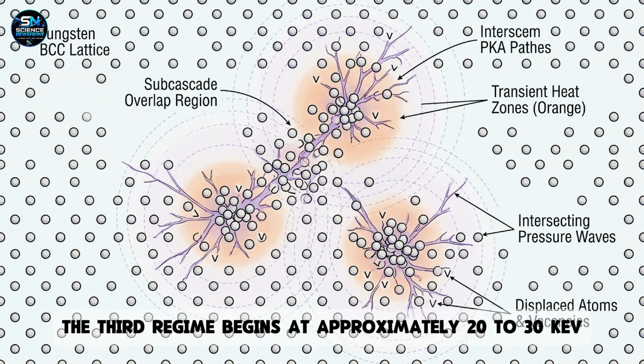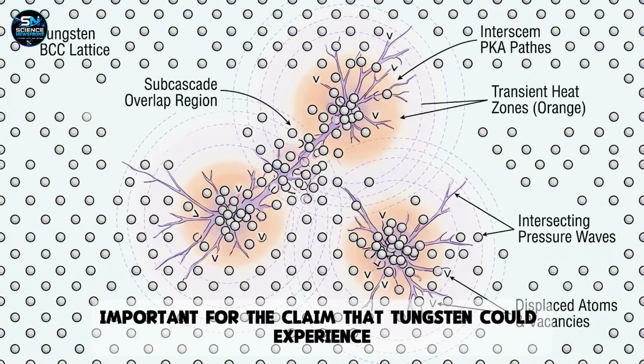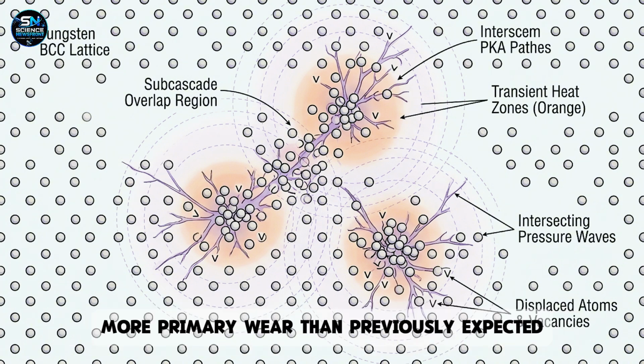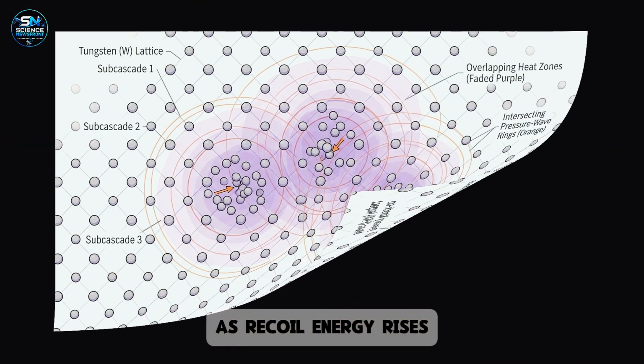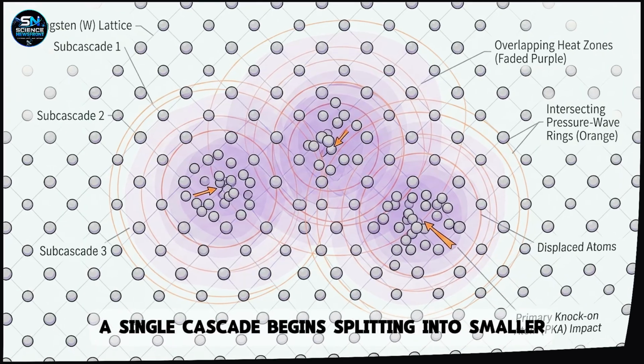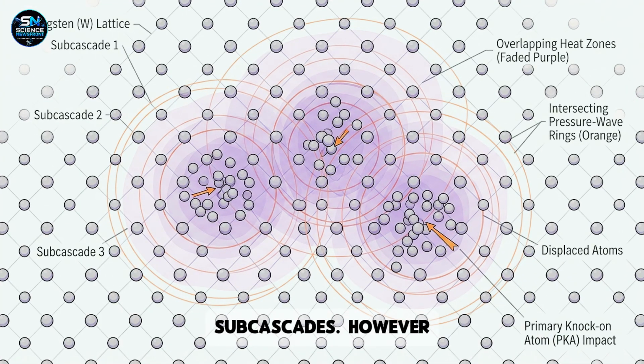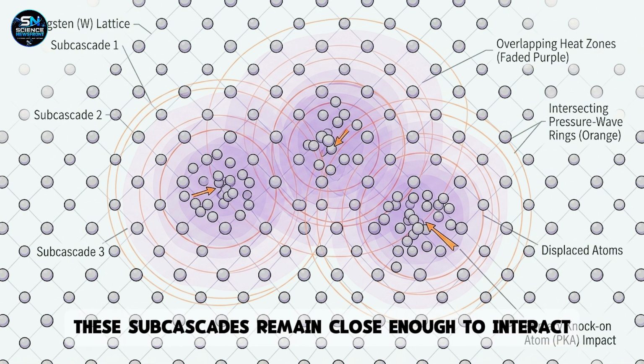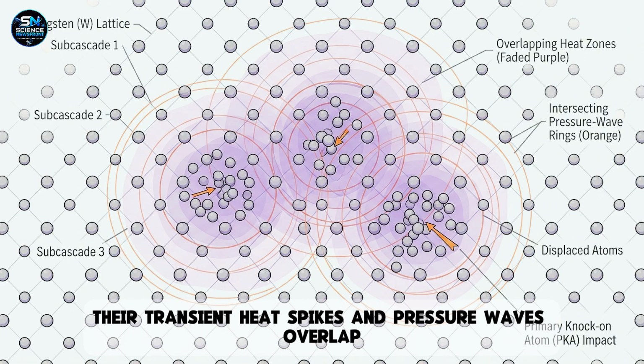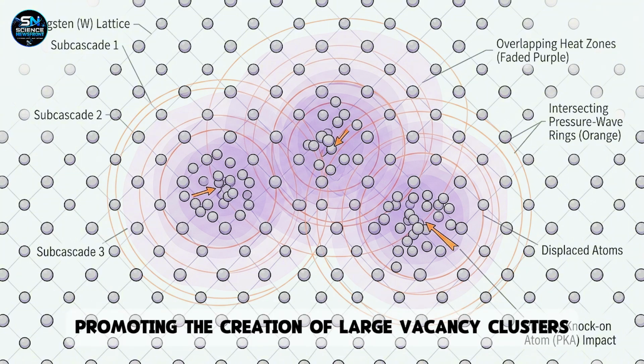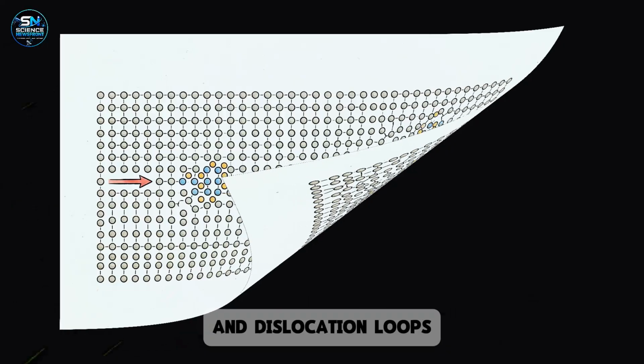The third regime begins at approximately 20 to 30 keV, and is the most important for the claim that tungsten could experience more primary wear than previously expected. As recoil energy rises, a single cascade begins splitting into smaller subcascades. However, these subcascades remain close enough to interact. Their transient heat spikes and pressure waves overlap, promoting the creation of large vacancy clusters and dislocation loops.